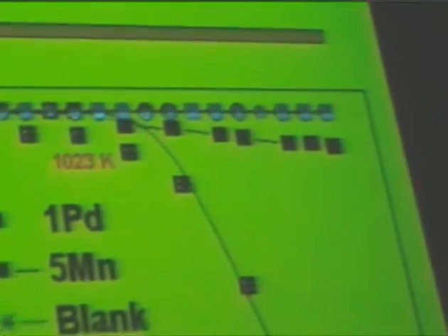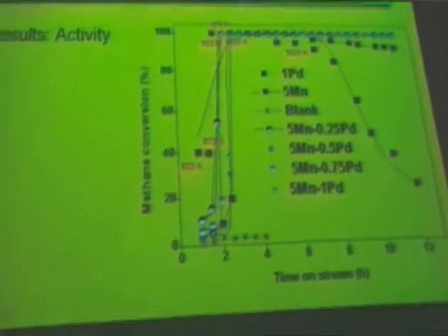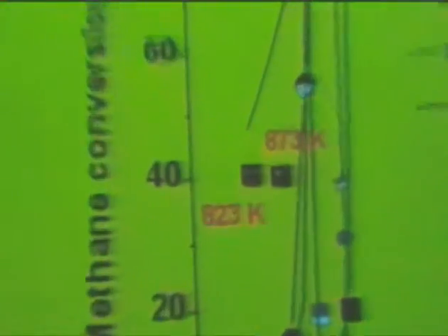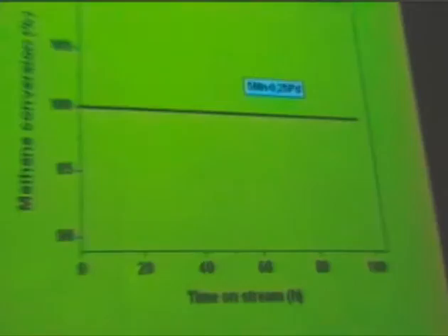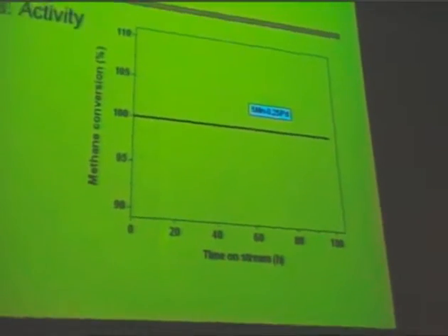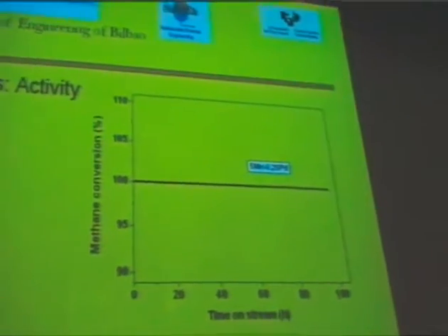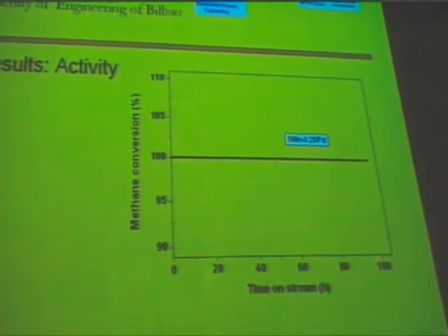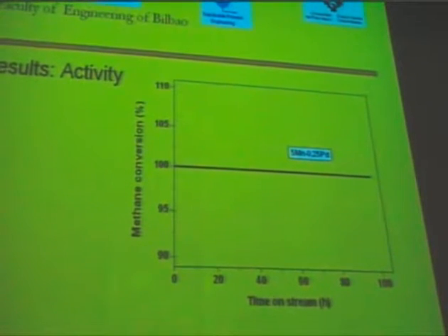In the case of the bimetallic catalyst, during the time on stream, it is not observed any deactivation. To analyze this stability, a new test was designed with 100 hours, and you can see that during 100 hours no effect of deactivation is observed.